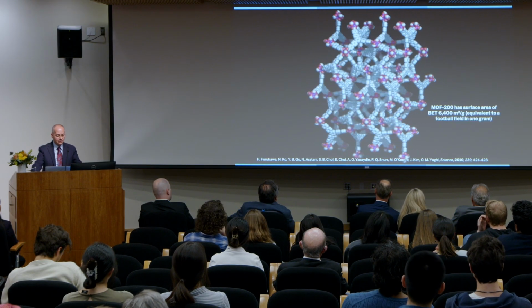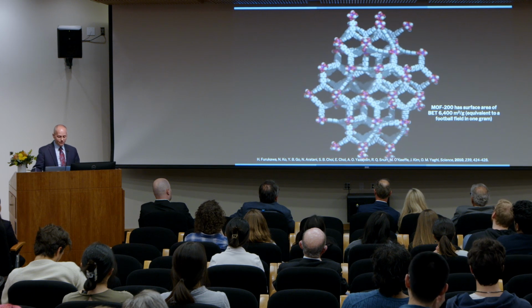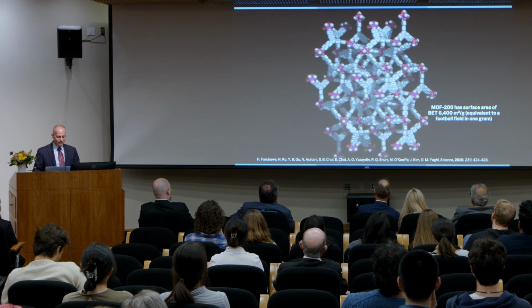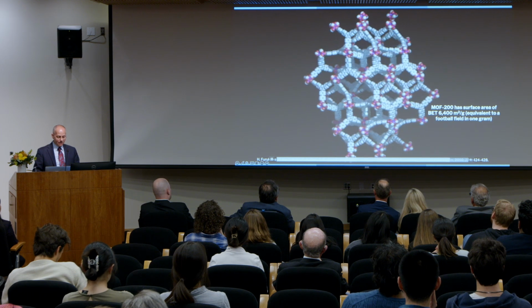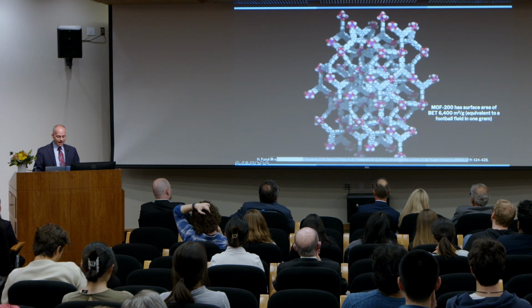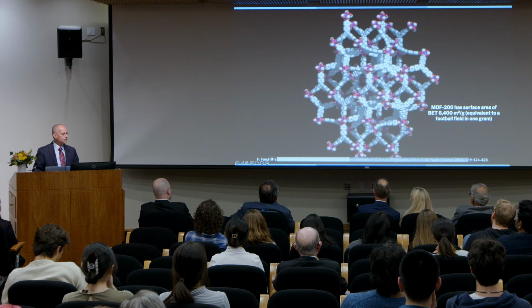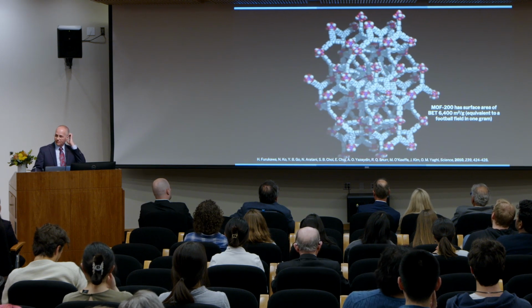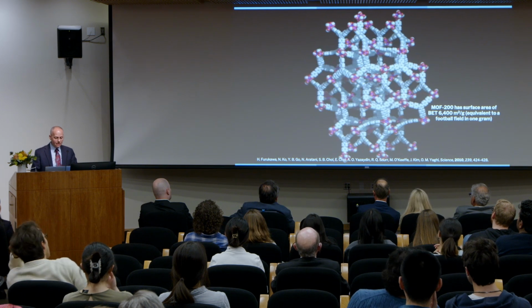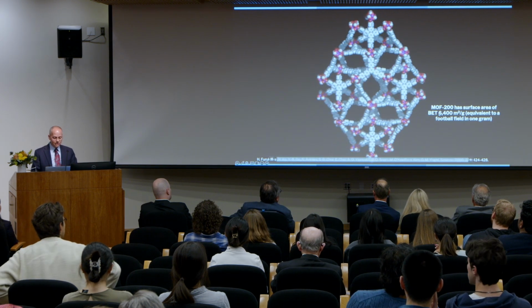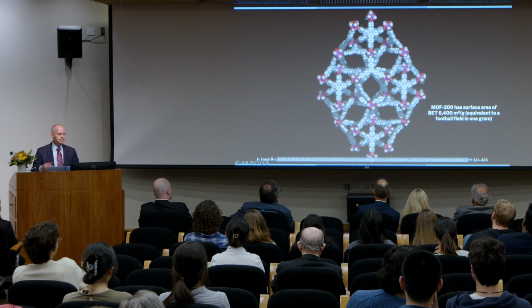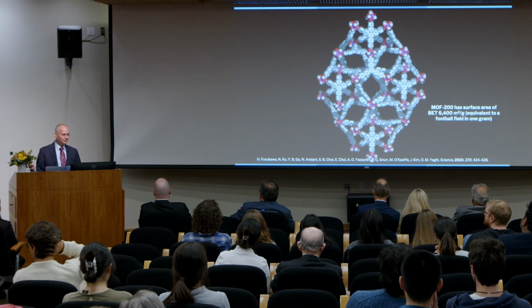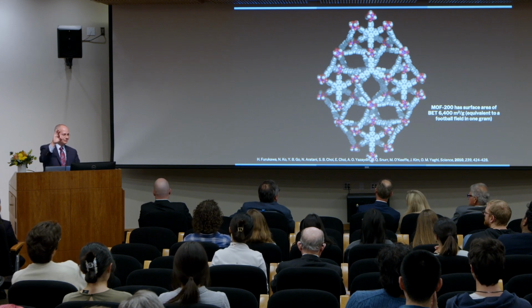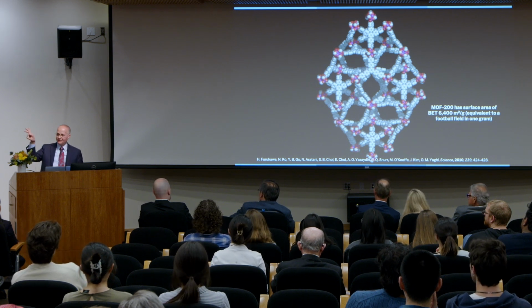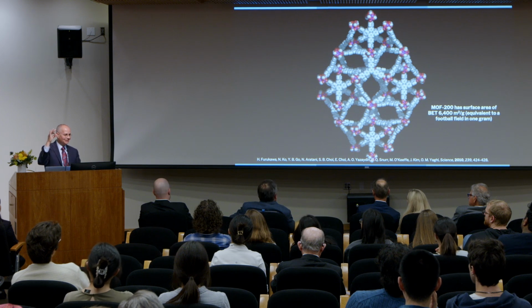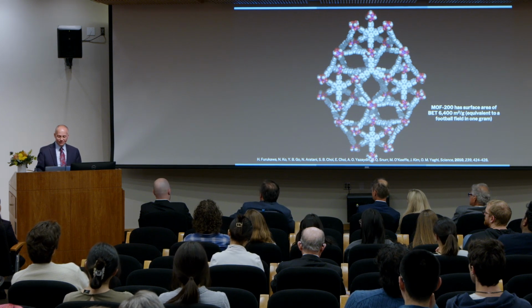And if your eye could see a molecule, a MOF, it would see something like this, where you have in gray the organic part and in pink the inorganic part. And everything you're looking at is a place onto which CO2, hydrogen, water, or other gases can bind. The surface area of this particular material we call MOF-200 is 6,400 square meters per gram. That's the footage of an entire football field, trapped in 1 gram of material that is no bigger than an American quarter, okay? Or American dollar, I should say.